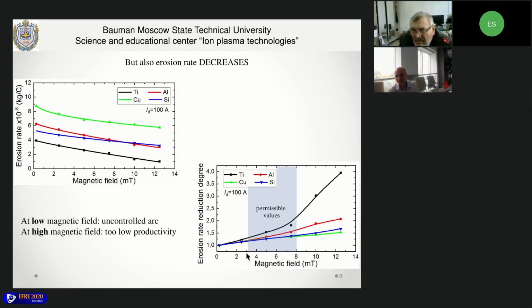So from this data, we can conclude that the optimal magnetic field to use for industrial vacuum arc evaporators is from 3 to 8, or maybe 10, millitesla. Within this range, at 3 millitesla the cathode spot is already fully controlled, and at 8 or maybe 10 millitesla the cathode spot is fully controlled, but the erosion rate reduction is not so drastic.